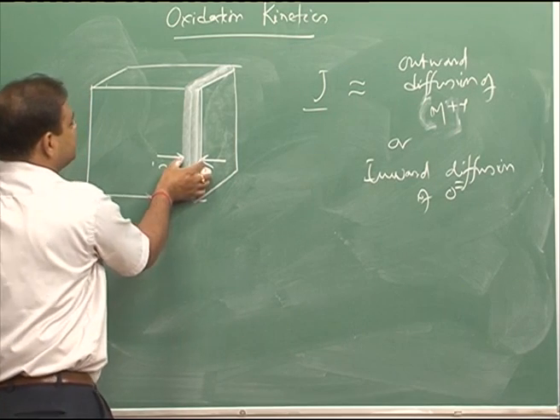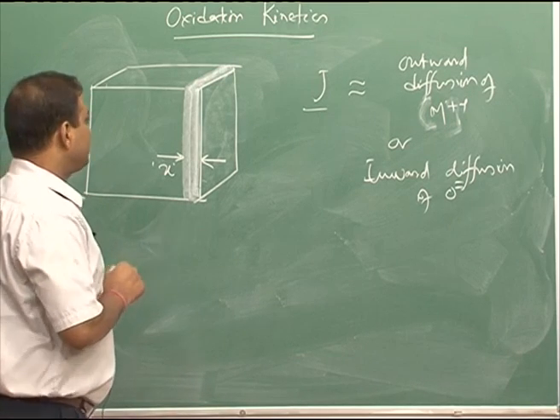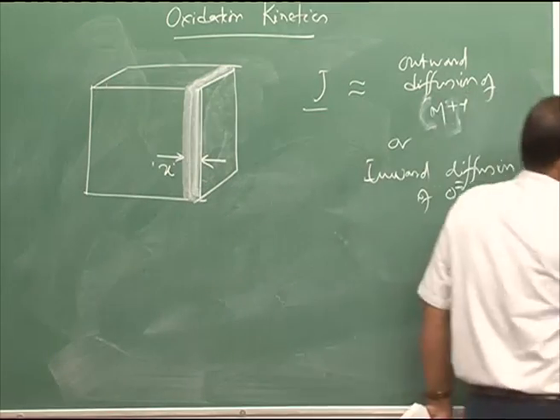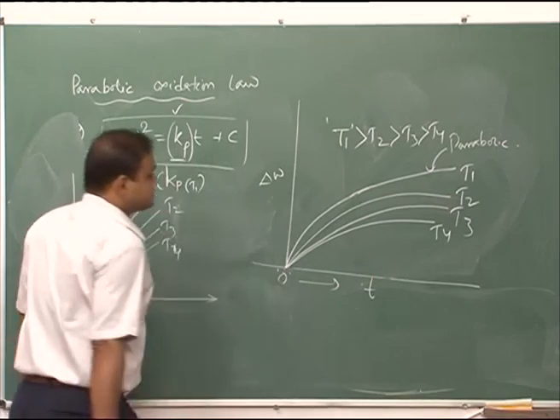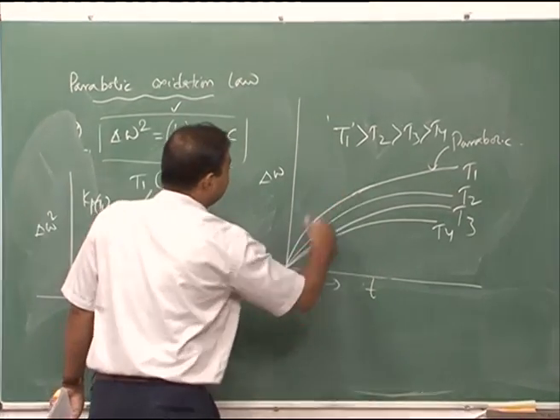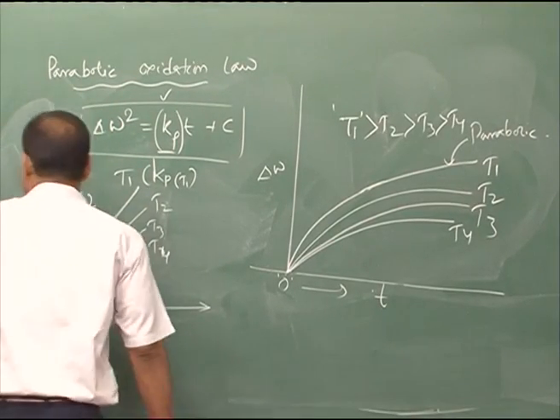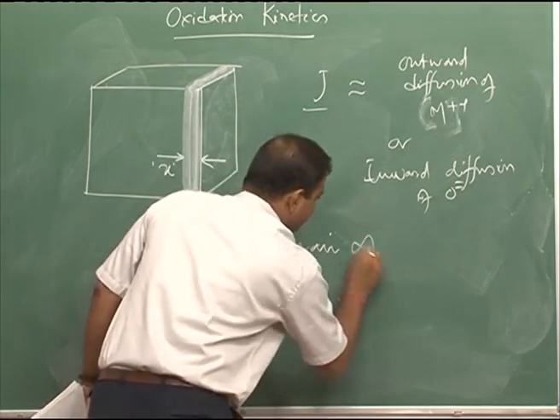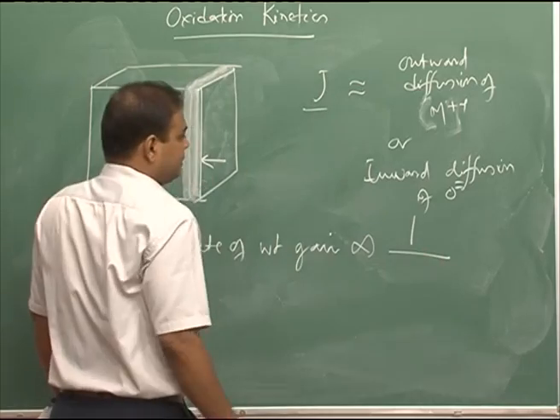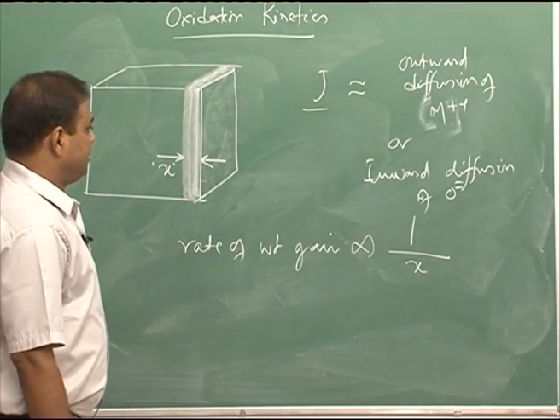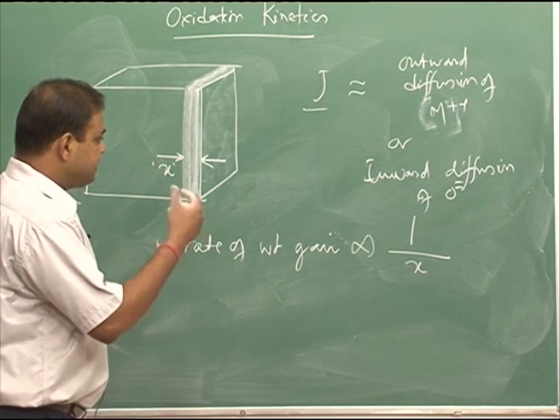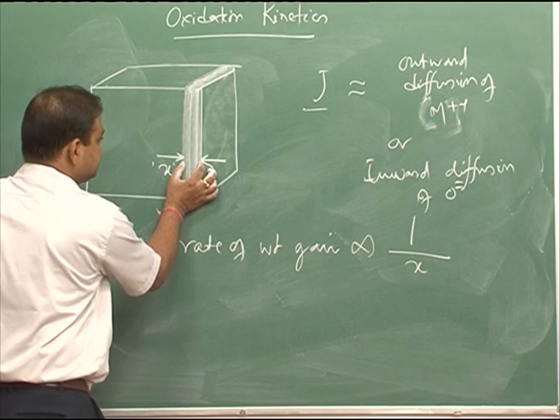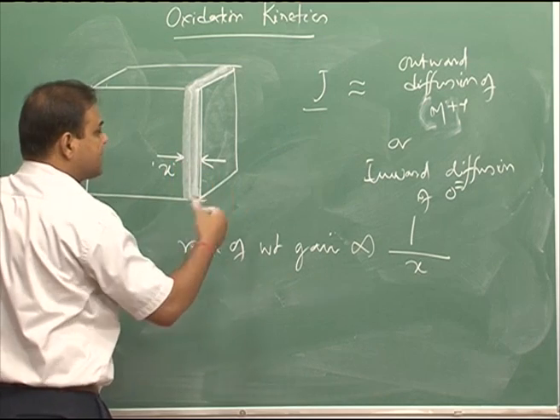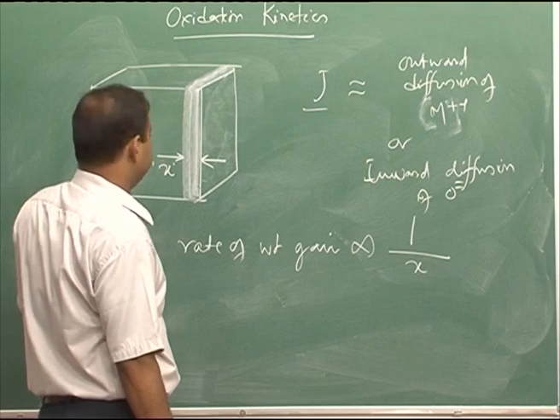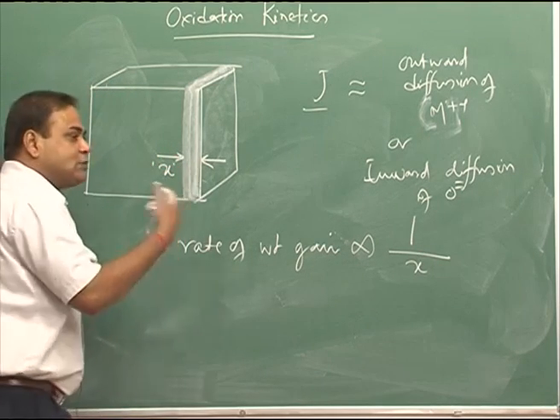Now, that could be proportional to the increase in thickness. In another way, if we consider this graph, as we increase the time for oxidation, we see the rate of weight gain is decreasing. So, that means the rate of weight gain is proportional to the inverse of thickness. Why? Because as you increase the time, your thickness is increasing, the rate of oxidation is decreasing, or the rate of weight gain is decreasing, or the rate at which thickness increases would also decrease.